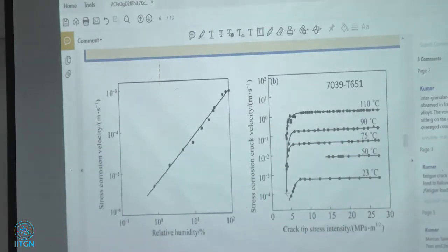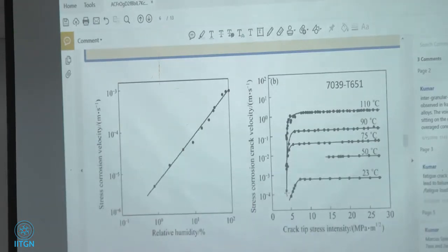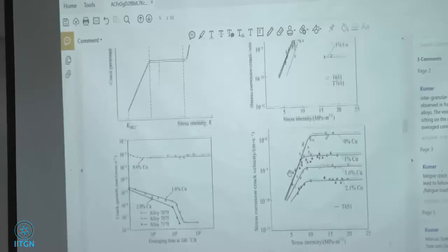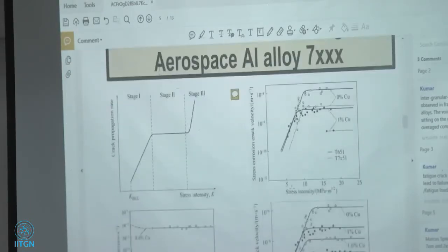Yes, he has kept the temper constant. I see what you're saying. So the dark lines are T6 and the dotted lines are T73, T751, T7351 or something. T6 is your peak aged and T7 is your over aged. So he has taken that sample, put it in the furnace and aged it for a little bit longer time, and he got the over aged temper.